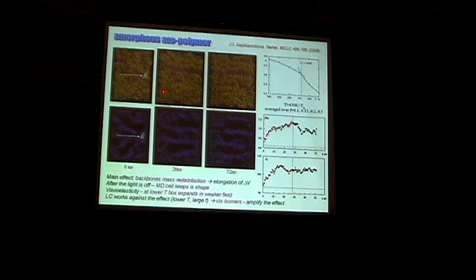So basically, what we found is that the main mechanism for the deformation in this case is rearrangement of the backbones.